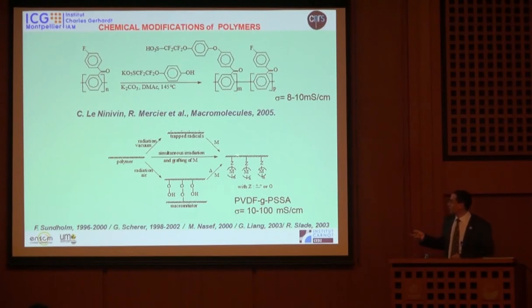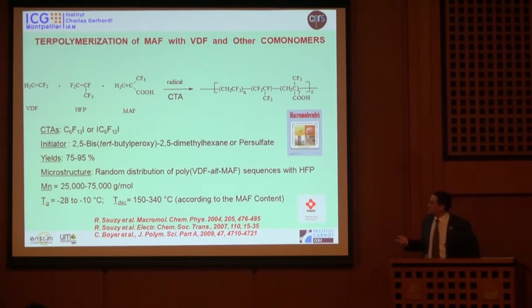So in this case, you have a fluorinated backbone in which you have a graft made of a monomer. And if you take styrene, which is very easily polymerizable under radical condition, so under macroradical or macroperoxide, you can have a graft copolymer, let's say with PVDF or PTFE-graft-polystyrene, that you can functionalize by acidification in H2SO4, for instance, in order to make some graft polystyrene sulfonic acid. And for instance, Suldom in Finland achieved some conductivity up to 100 millisiemens per centimeter. However, the problem is durability, because this styrene compound can undergo some beta elimination and is not very appropriate in long-term fuel cell test.